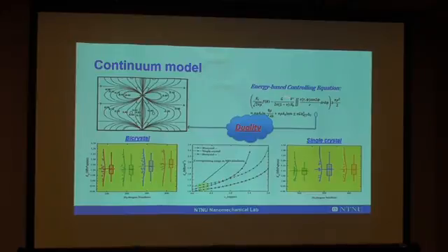So let's solve this equation, and we can obtain the critical K1 for the dislocation emission as a function of hydrogen concentration. We can observe that for any specimens, the K1D, which means the critical K1 for dislocation emission, will increase with the increasing hydrogen concentration.